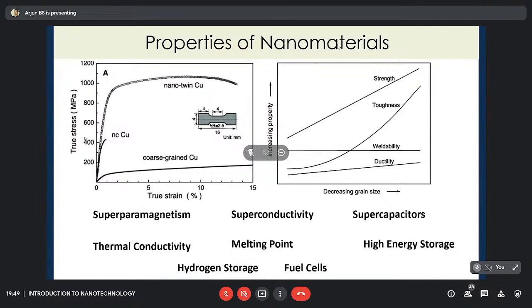In the case of this coarse-grained copper, when we introduce some dislocation or defect, it actually propagates through the entire length of the material, and it affects the strength of the material. However, in the case of nanomaterials, we have very much control over the grain dimension, which gives this kind of copper, fabricated using nanotechnology, very high strength.